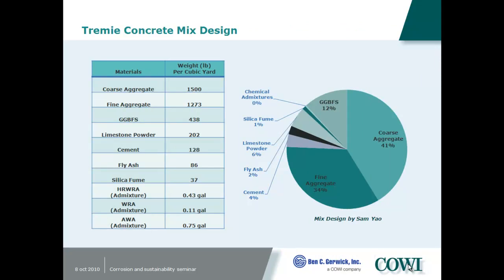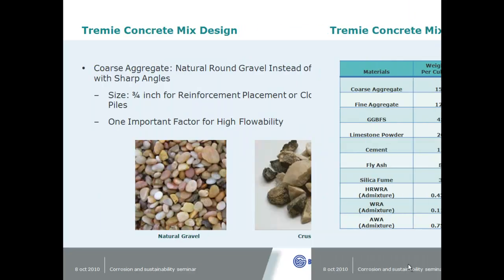Here is a Tremie concrete mix design. You can see the blast furnace slag. We used coarse aggregate and fine aggregate. Some of the key features here, we also used limestone powder. That's a little bit unusual, but it does have a little bit of reaction with the cement, and also reduces the heat. We had fly ash as well and silica fume. Here's the high range water reducer, the low range water reducer to extend the workability life. And here's the anti-washout admixture.